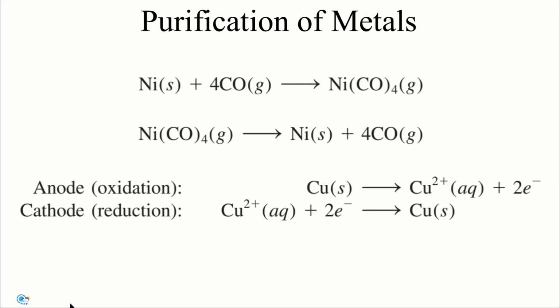Pure metallic nickel is recovered from this nickel tetracarbonyl by heating the gas at 200 degrees. The carbon monoxide that is released is recycled back into the process.